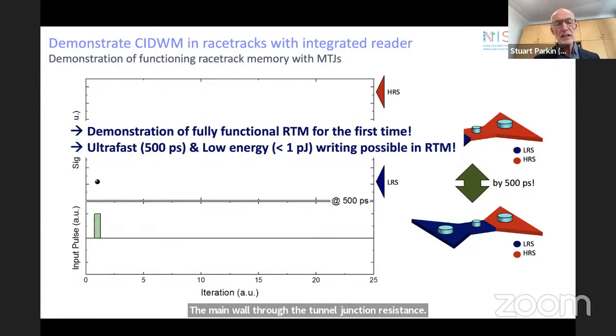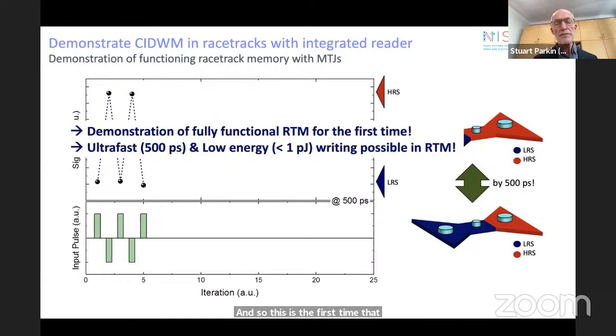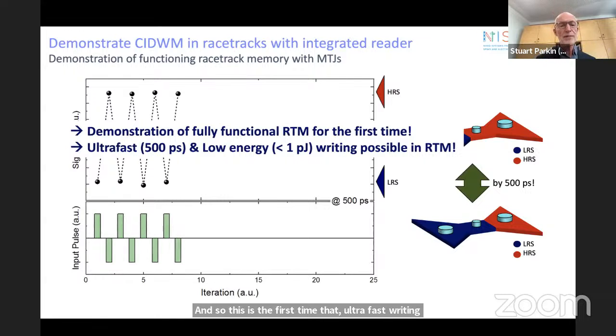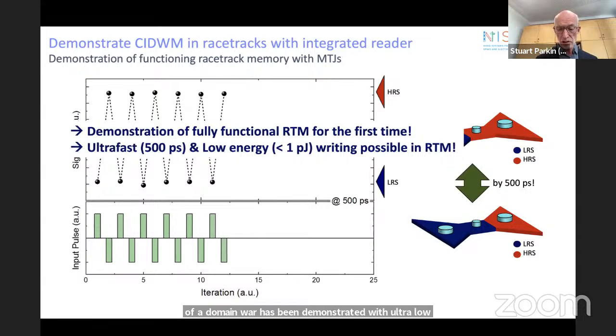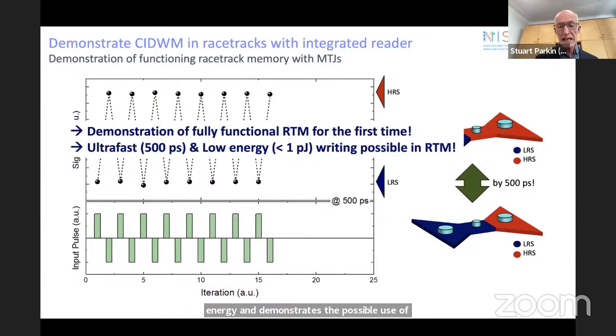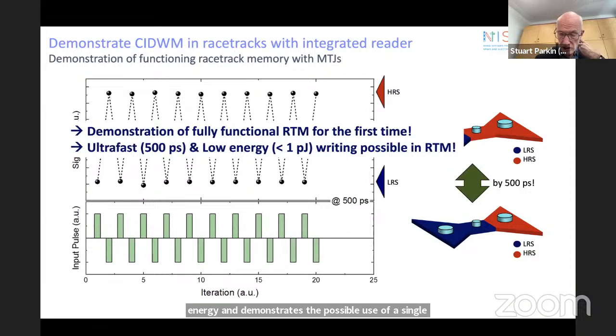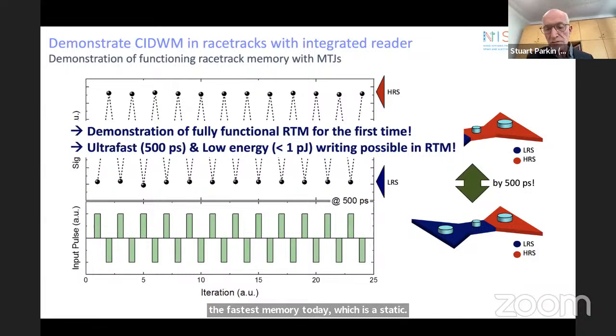And so this is the first time that ultrafast writing of a domain wall has been demonstrated with ultra low energy, and demonstrates the possible use of a single domain wall racetrack as a replacement for the fastest memory today, which is static random access memory. Those memories typically occupy 50% of a chip today and take a lot of area in the silicon. If we could replace them with a single domain wall racetrack, we would use up much less area, and moreover, it would be non-volatile. So this would give a huge advantage. So we think this could be the very first application of racetrack. Certainly easier to build a single domain wall racetrack than a multi-domain wall racetrack.